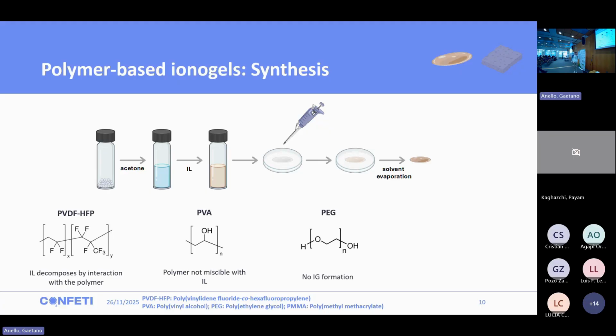So if we move to the first approach, we decided to use a simple procedure that is dissolving some polymer in an organic solvent, mixing with the ionic liquid, and then casting it in plates and letting the solvent evaporate. In this approach, we tried several polymers, but we were not able to obtain membranes with good physical properties, either due to decomposition of the ionic liquid, or, as you can see here, stability problems, where you can observe that the ionic liquid leaks from the polymer matrix.